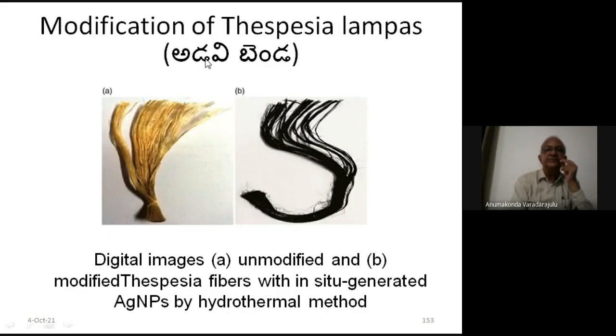So this is the Thespesia lampas fiber. This is original fiber treated with sodium hydroxide. It is having the natural color, brown color. But we dipped these fibers in hot silver nitrate solution at 80 degrees Celsius for 24 hours, as we described in the hydrothermal process. After 24 hours, the color changes to almost black. The color change indicates the generation of the nanoparticles inside.